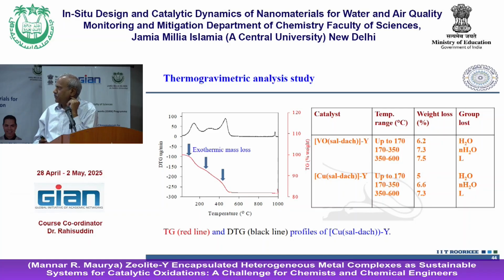You will see that going from 110, like 100% up to 80%, it is not going beyond that. It is so stable, meaning partial decomposition has occurred in 2-3 different places. In the beginning, some water molecules, then up to 350, all the water molecules that were trapped, and then at the end, between 350 and 600, that is only due to the decomposition of the metal complex. So that could give an idea. Three different decomposition temperatures are seen there.